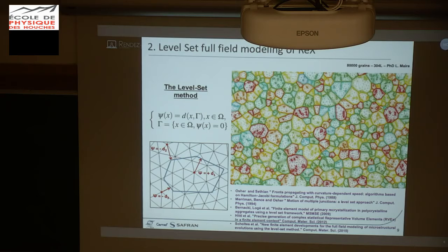But another message is: what could be the interest of such finite element mesh adaptation? For example, if you want to simulate grain growth by capillarity, intragranular information is not important. All is defined by the capillarity and the energy at the grain interface and by the interaction between second phase particles and the grain interface. And in this case, of course, it is interesting to use a coarse mesh inside the grain and a fine mesh at the grain interface. And we have proved in the past that this numerical strategy is interesting in 2D, but I will show you in another presentation that in 3D it's not the case.